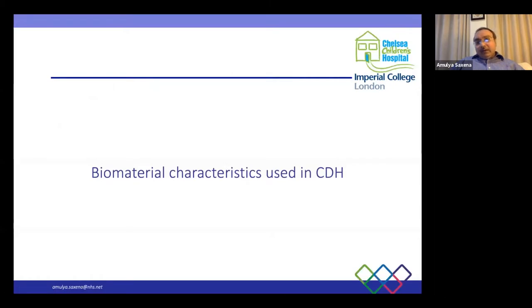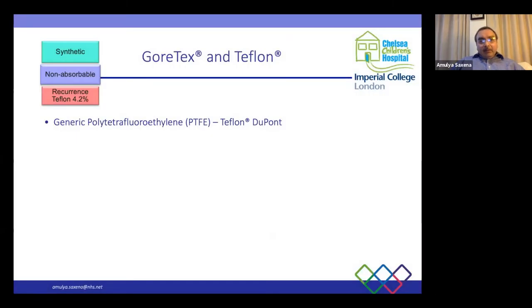Now, we look into the characteristics of these materials so you get an idea of what has been used and what works and what does not work. The most important, I've posted on the top left-hand side what type of material it is, if it is absorbable or non-absorbable, and the recurrence rate. When you see Gore-Tex and Teflon, people confuse them in the reporting. Teflon is generic PTFE, while Gore-Tex is expanded PTFE. So there are initial reports that mention that we used Teflon. I'm not very sure whether it was Teflon itself or Gore-Tex that was used in these patients.